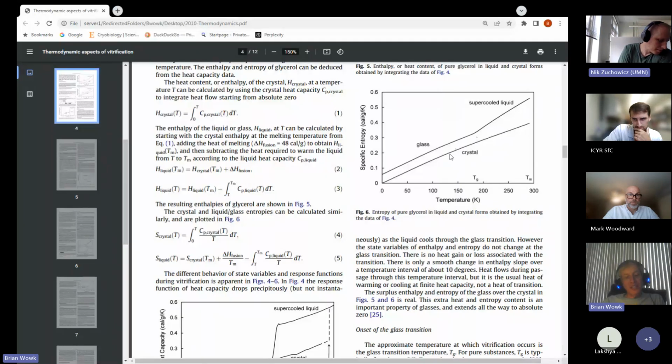So all that nucleation is going on has got to be heterogeneous, which means that it may be time limited. If you wait long enough, you may just find that it maxes out once you've exhausted your population of heterogeneous nucleators. I don't think it's going to go on without limit, but I would just like to see some DSC data.